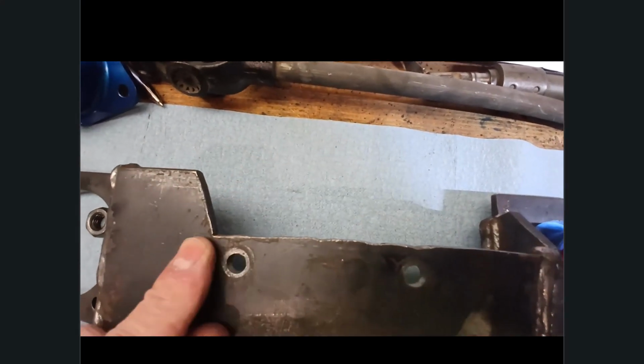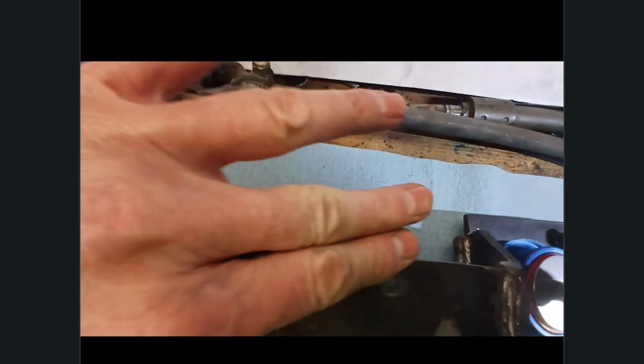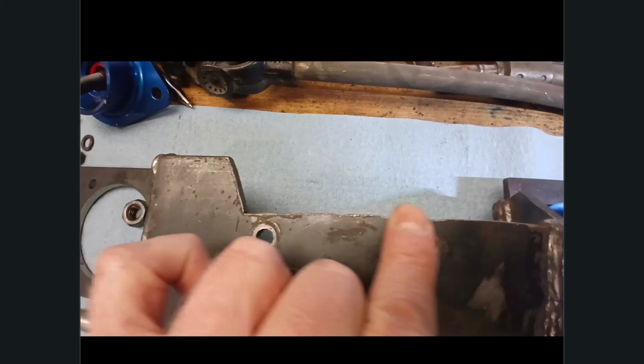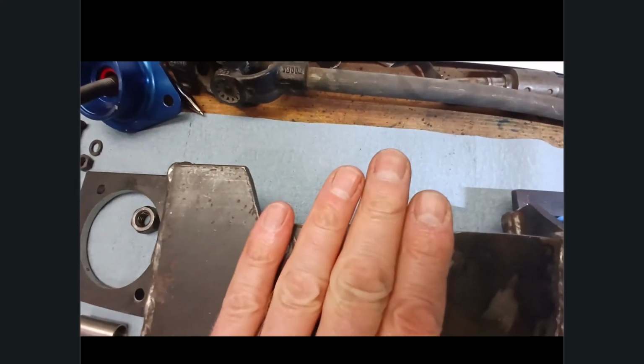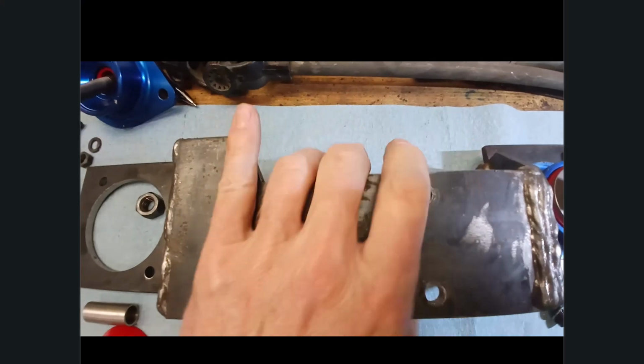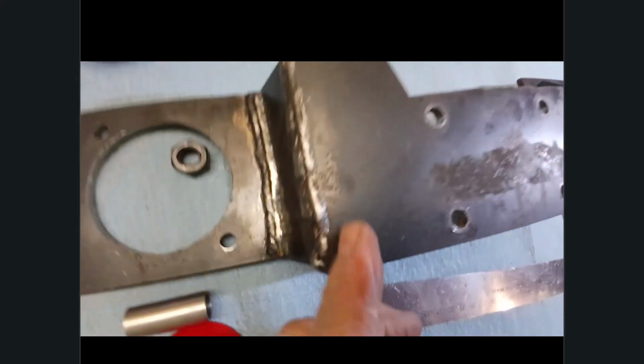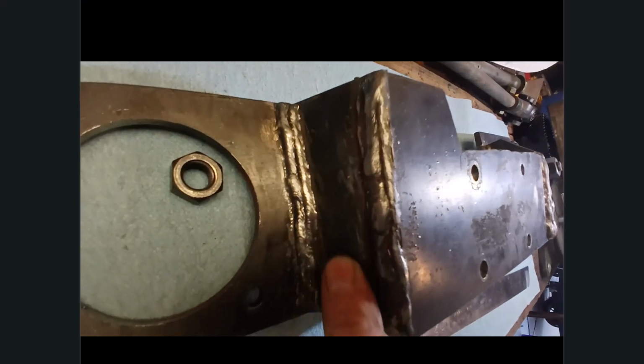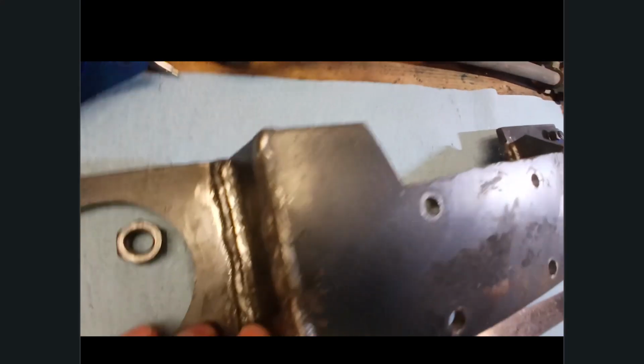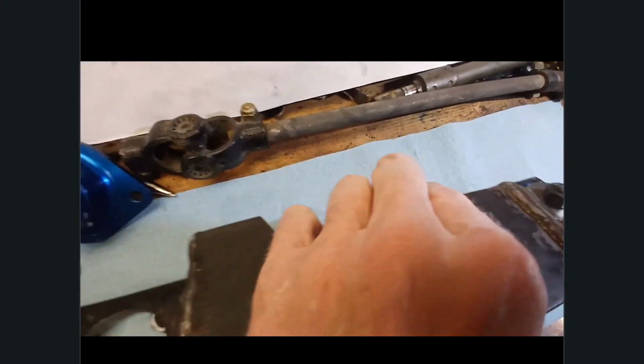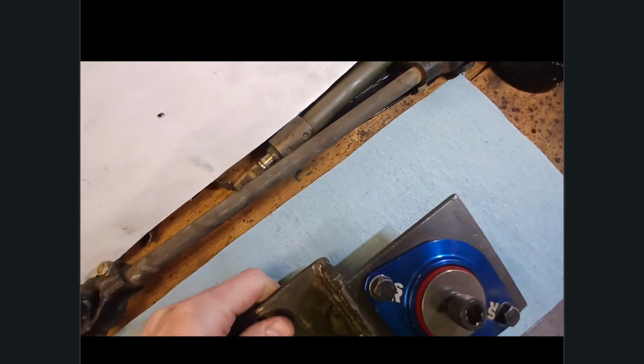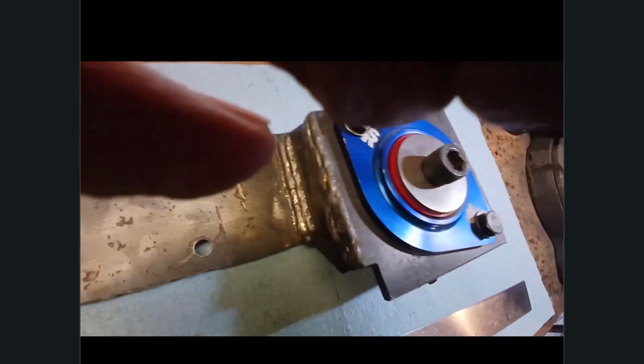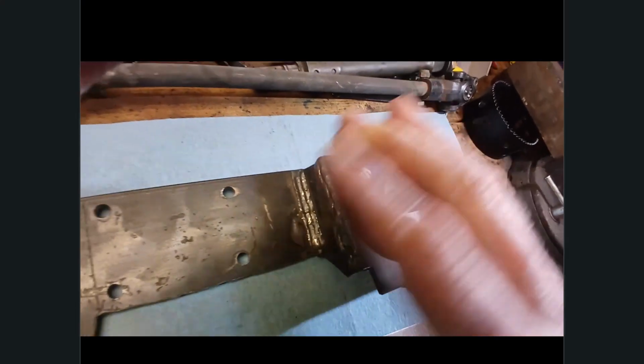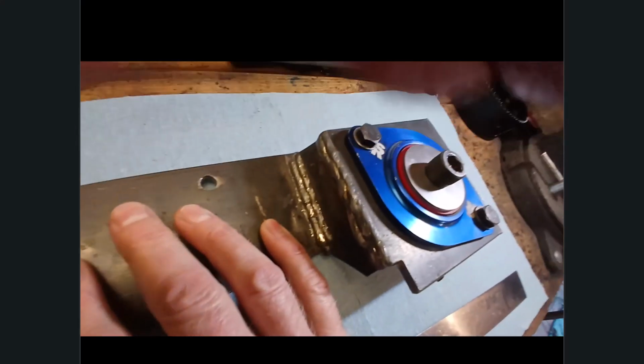I had to cut this out, because the cast aluminum for the transmission is right here, occupying this space. So with this little divot cut out here, you then bolt this 8-inch piece onto your transmission. Then these smaller pieces are not welded in yet, obviously. And then when you're looking up, what you're going to see from the bottom is this. This will be bolted in the bottom of the trailing arm mount. This is bolted into the bottom of the transmission.